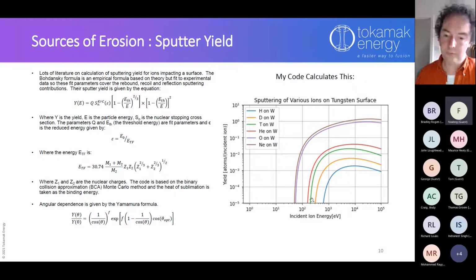We have mechanisms of dropping this ion energy. So in the core plasma, we've got about 10 keV, so it's up here somewhere. So we've got to drop it by 2 orders of magnitude. There are mechanisms for doing that. One of them, unfortunately, is what we call seeding with neon. We can use nitrogen as well, where you put in a gas.